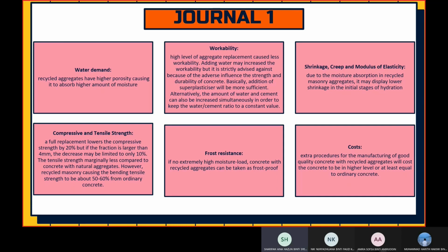The third property is shrinkage, creep, and modulus of elasticity. Due to the moisture absorption in recycled masonry aggregates, it may display lower shrinkage in the initial stages of hydration. In case of total replacement of recycled masonry, shrinkage may be about 40% higher, which will increase the creep by 15 to 40% and decrease the modulus of elasticity by 10 to 30%.